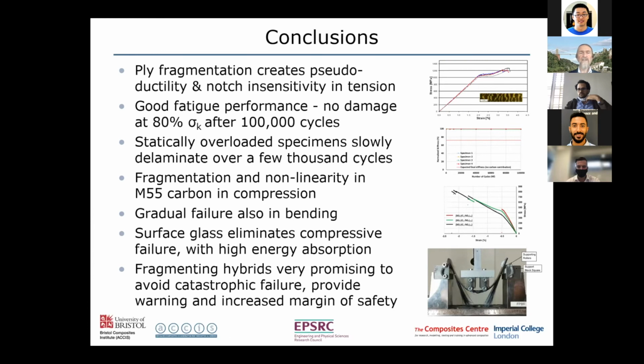We found that the fragmentation and non-linearity can also occur in compression, depending on the fibre, but certainly for the M55 high modulus fibre, we can get a fragmentation and non-linear response. The challenge is when you have a bending application, you have both tension and compression. So it starts to get quite complex, and the compressive and tensile failure strains are different. So you need some careful design to get the sort of response you want. We've demonstrated we can get a nice gradual failure also in bending, and that if we put a surface glass layer, then we can eliminate the compressive failure and give a very high nonlinear large deformation response with high energy absorption.